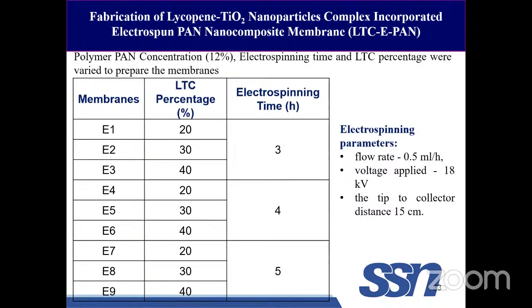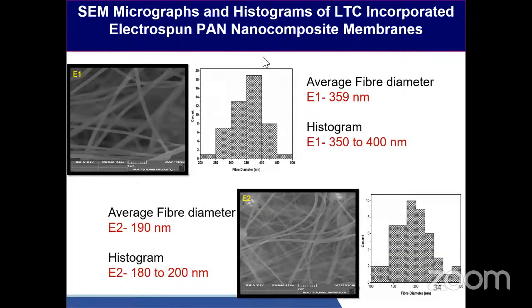So we characterized the fiber diameter. For 20% loaded nanofibers, the average fiber diameter is about 359 nanometers, and the distribution of the fibers is between 350 to 400 nanometers. Whereas for 30% incorporated nanofibers, the average fiber size is about 190 nanometers, and the range of distribution is between 180 to 200.